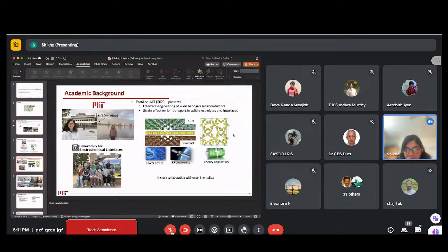So what will happen through this bottleneck, one atom will hop from one side to another side. Suppose at the interface, the bottleneck size is reducing. So you are reducing the space to migrate, to diffuse one atom from one side to another side. And if your grain boundaries are formed in a way that they are making more space to transport the atom, we could have more diffusivity also. But it depends on the given system, what kind of system you have, and what kind of local mechanism defines the diffusion of your given conductor. So yeah, it depends. It will vary from metal to metal.